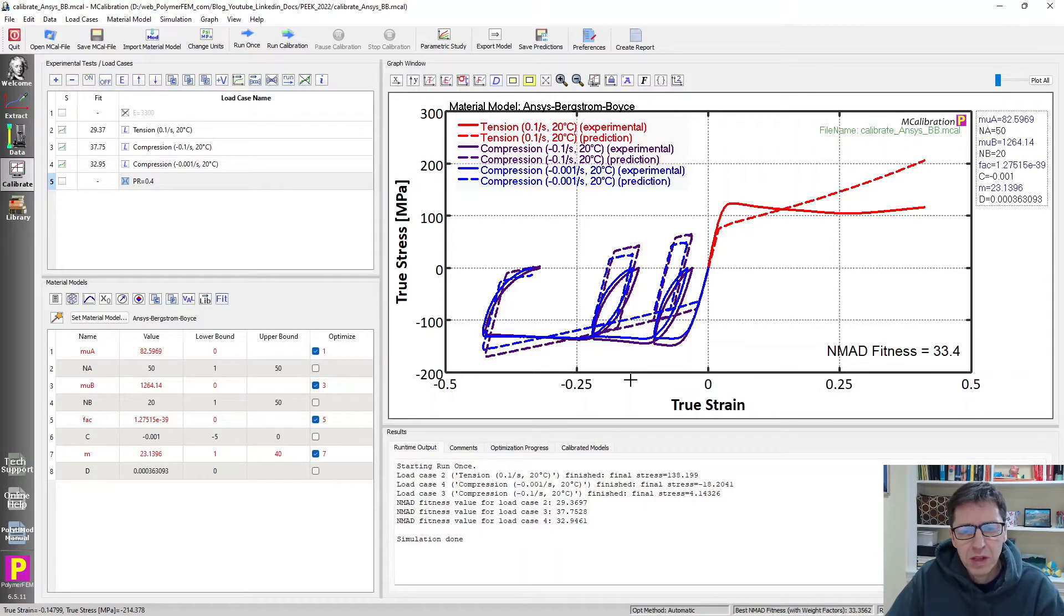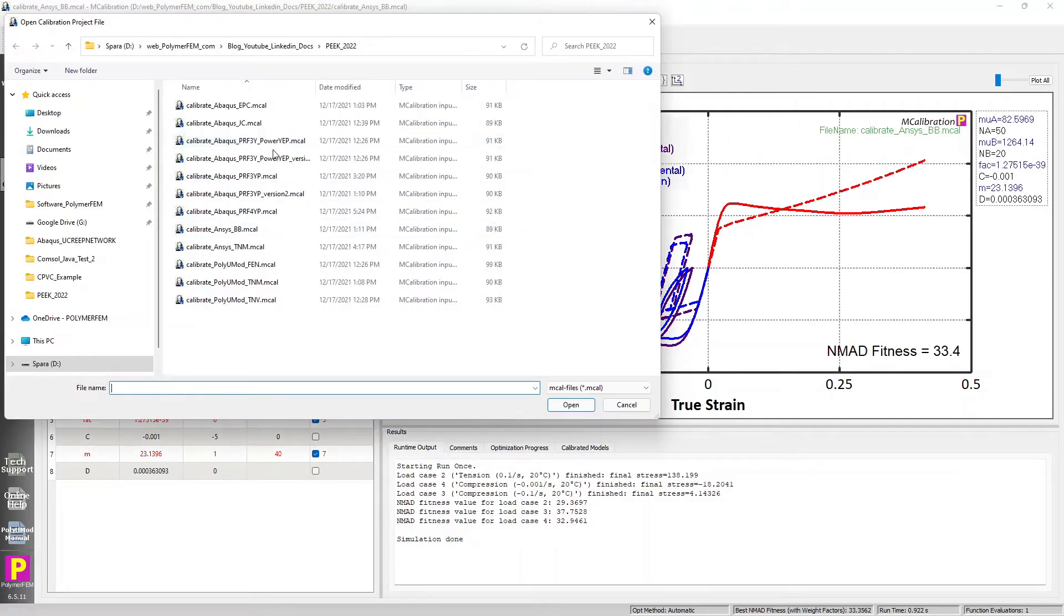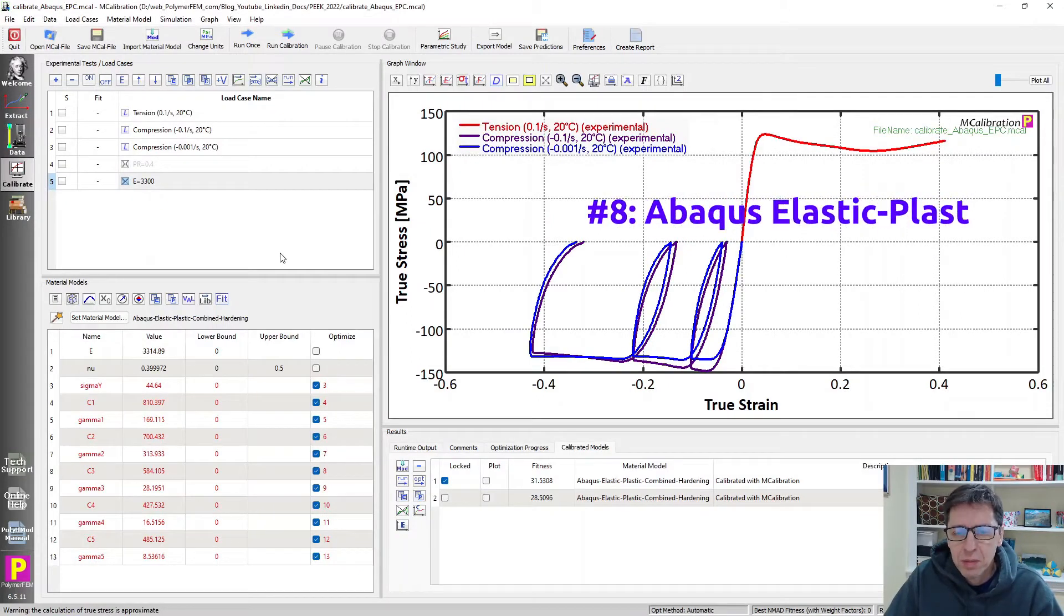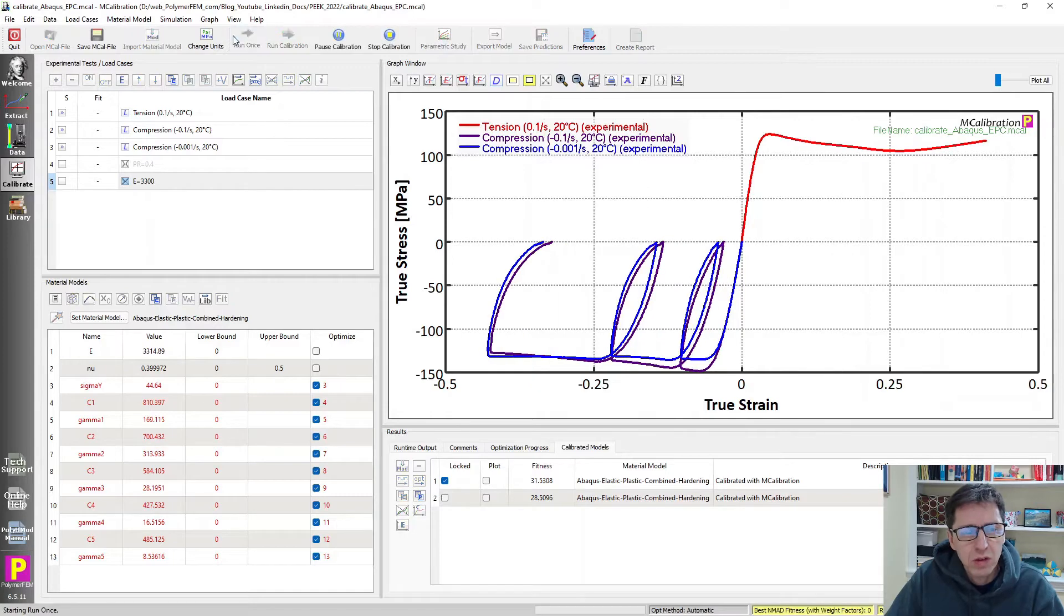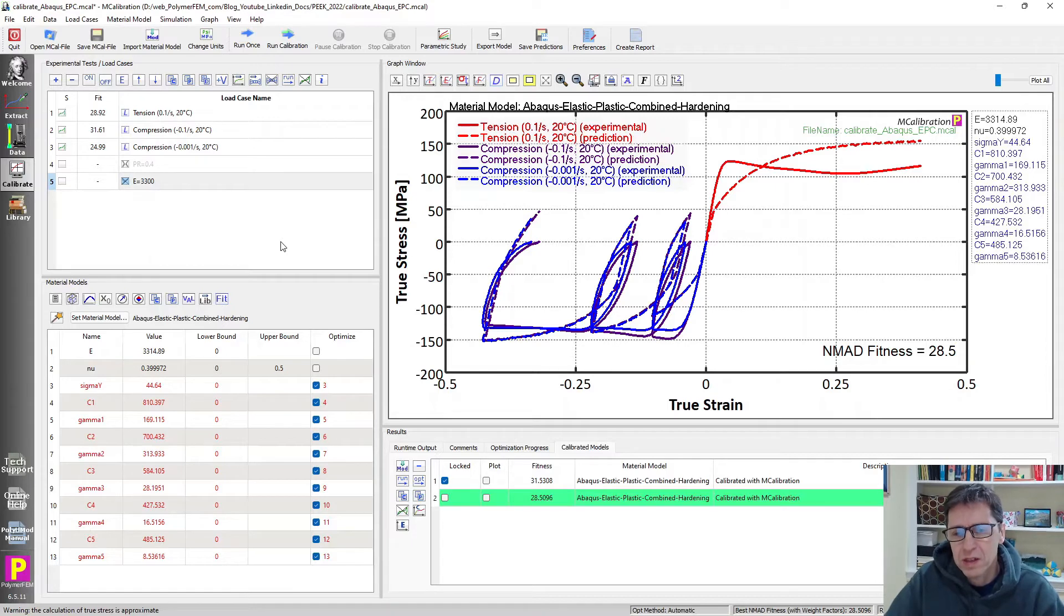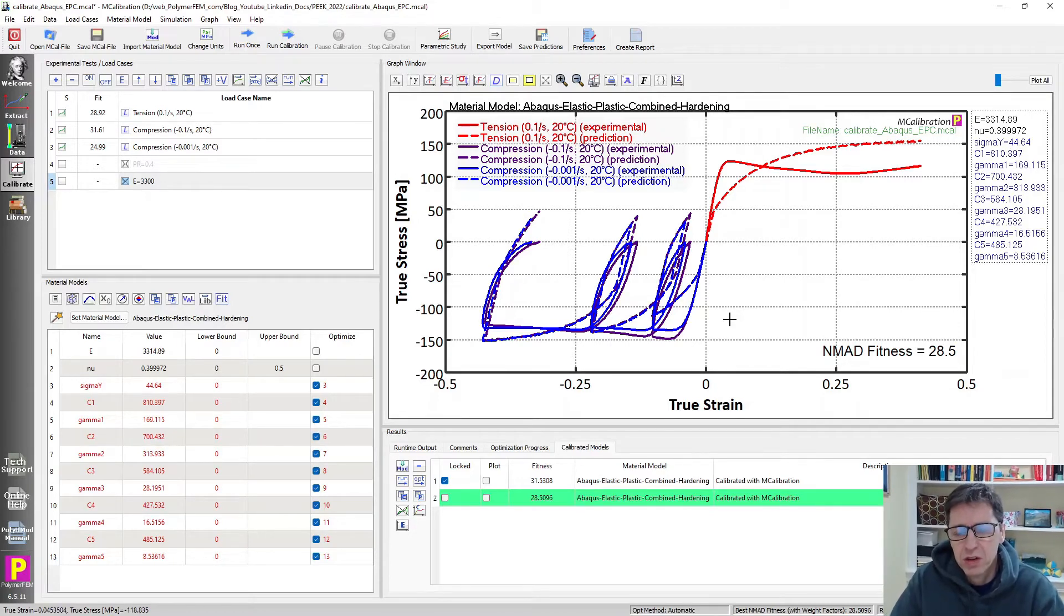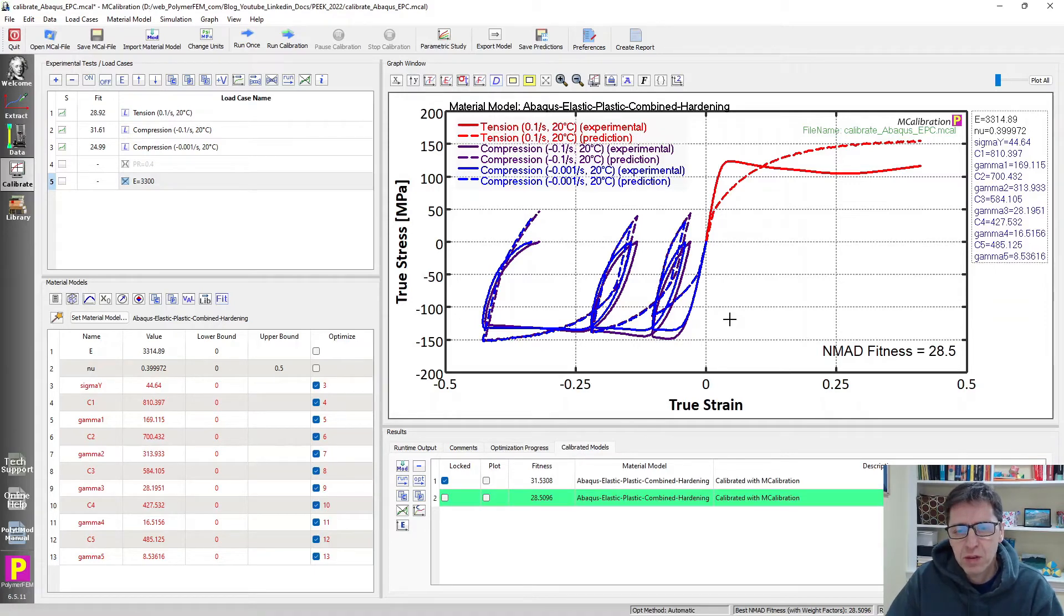Let's try something else. How about an elastic-plastic combined hardening plasticity model? So this is a model that I use in Abaqus. It's a combined hardening plasticity model. It's very easy to use and easy to calibrate. But as you can see here, it doesn't do very well in this case either. It looks a little better. The average fitness is 28%, but it's not an accurate representation of the data. No one can argue that this is a good model, I would say. So we need to look further to see if we can find something better.